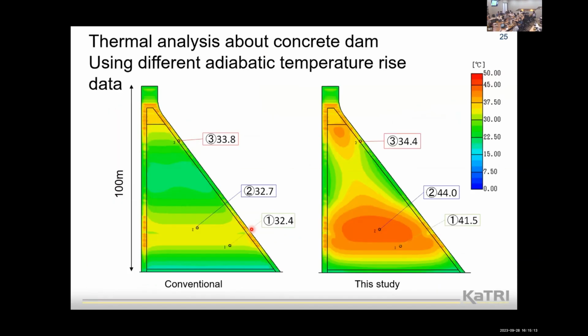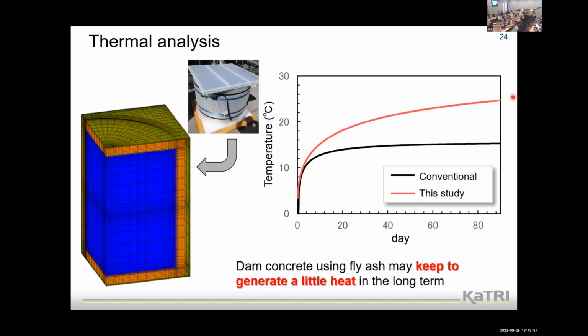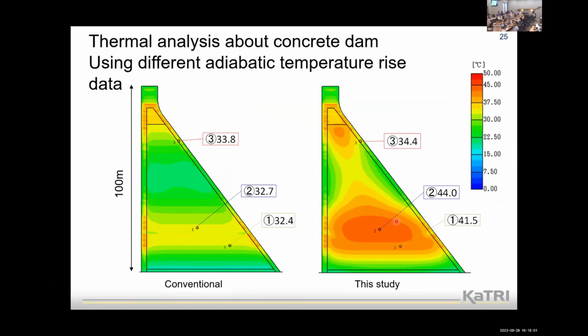Finally, this is a thermal analysis of a concrete dam using different adiabatic temperature rise data. This figure shows the result using conventional data. We usually use this equation, this data, and this value shows the maximum temperature at some point. And then we apply this new adiabatic temperature rise data to the dam concrete. It is about 10 degrees Celsius higher compared to the conventional data.